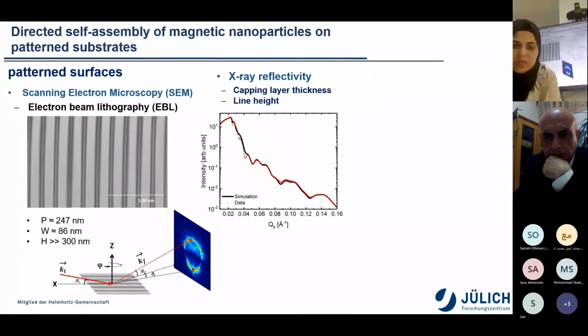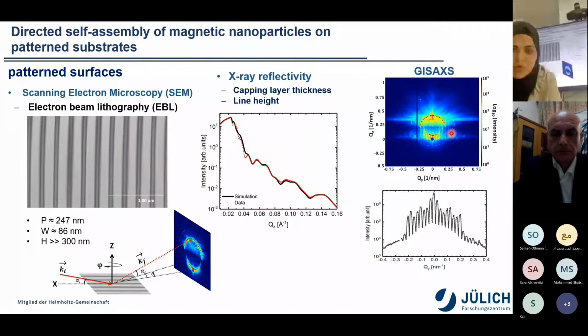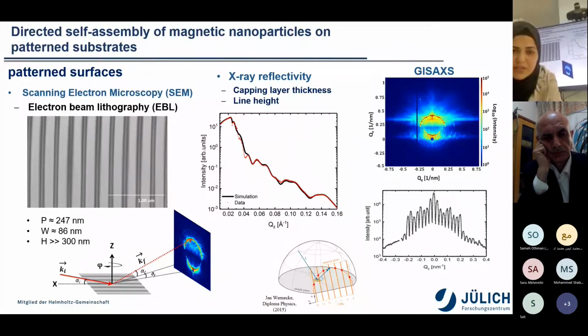Also, we performed GISAXS in order to study the lateral periodicity of this grating, and we performed the measurement with the incident beam totally along the grating lines. We end up with this pattern, where diffraction spots appear along a semicircle, which is due to the intersection of the Ewald sphere with the grating truncation rods. The radius of this semicircle is calculated as the sample-detector distance times the tangent of the incident angle. Furthermore, this pattern is sensitive to the accurate alignment of the direct beam along the lines.